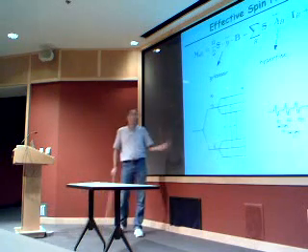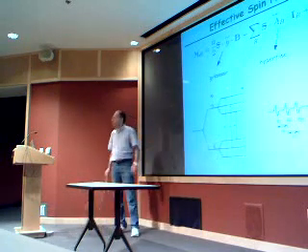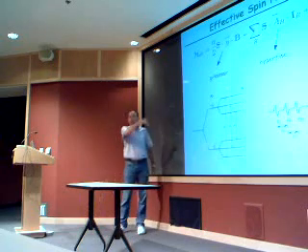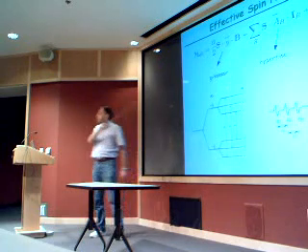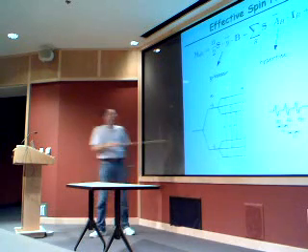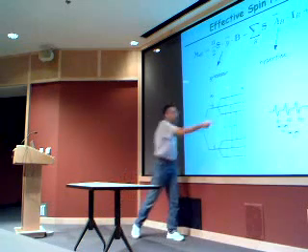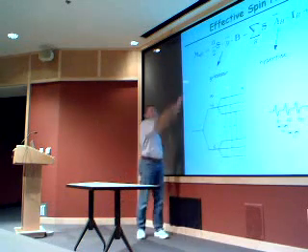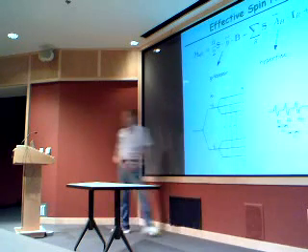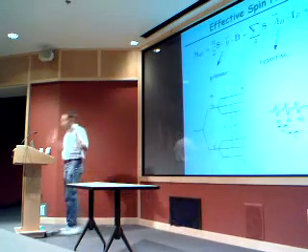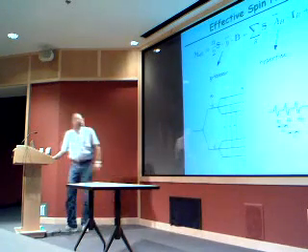Experimentally, what they do is that they hope to know the chemistry of their compound. They draw this diagram. Maybe it's much more complicated because you have more spins or higher spins. Then they simply take the experimental spectrum, fit it using this Hamiltonian, and extract these parameters, and the zero field spectrum. So it's just a matter of fitting your spectrum.